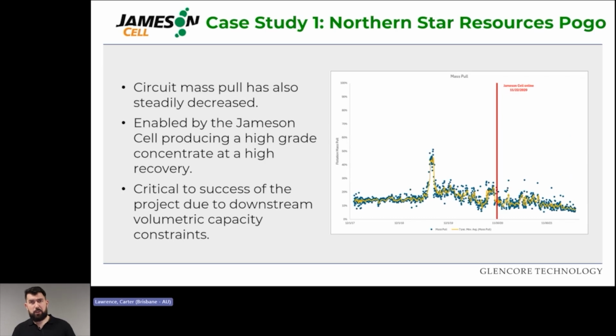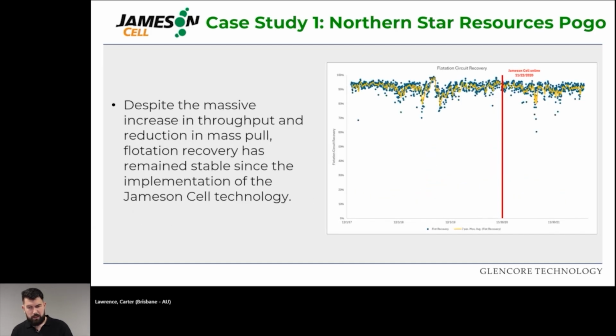Now, in that time, circuit mass pull has also steadily decreased. That's again enabled by the Jameson Cell producing a very high grade concentrate at a high recovery. And this was also critical to the success of the project because downstream of the flotation circuit, there were volumetric capacity constraints. So despite increasing the feed tons, they did not have a lot of volumetric capacity for the mass pull. Despite this massive increase in throughput, as well as the reduction in mass pull, the circuit flotation recovery has remained stable since the implementation of the Jameson Cell technology.